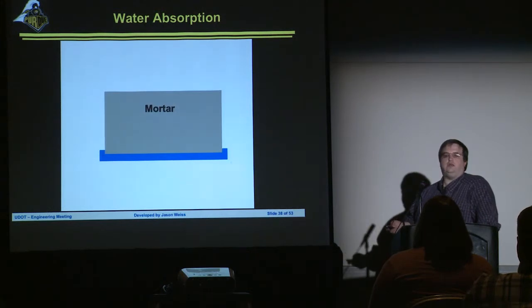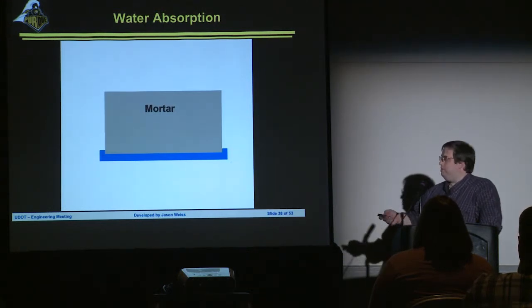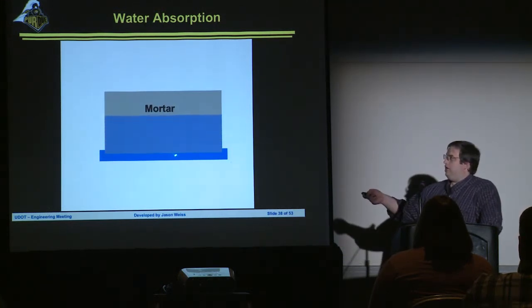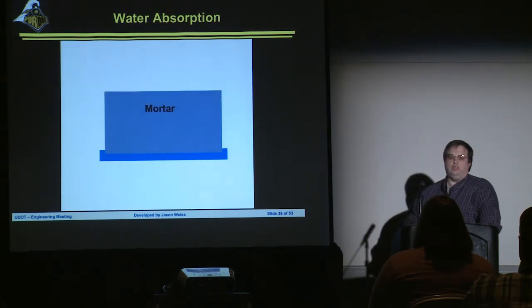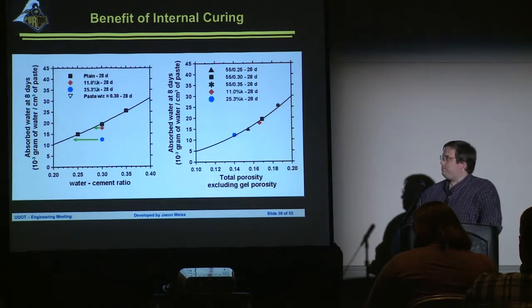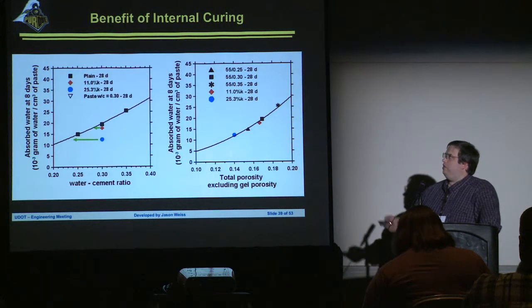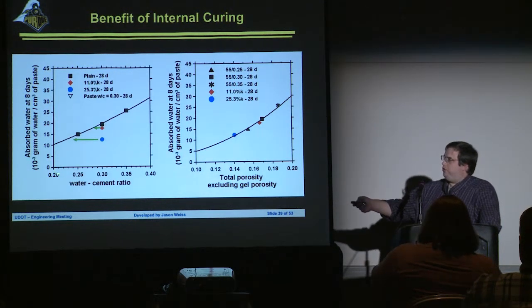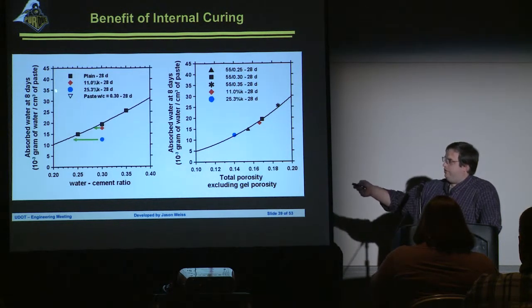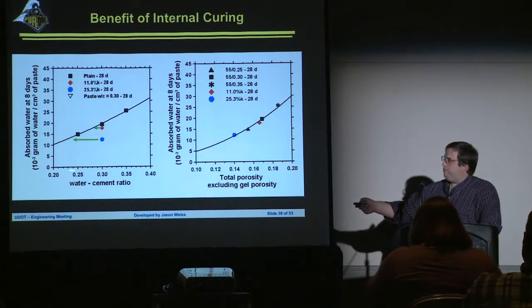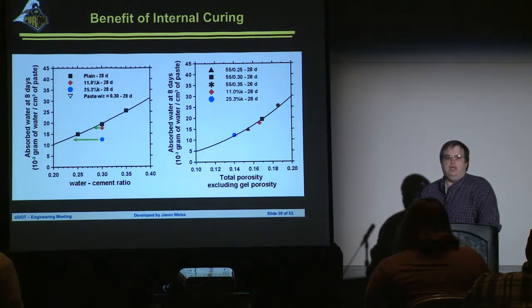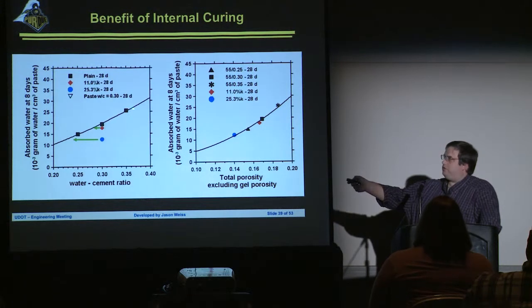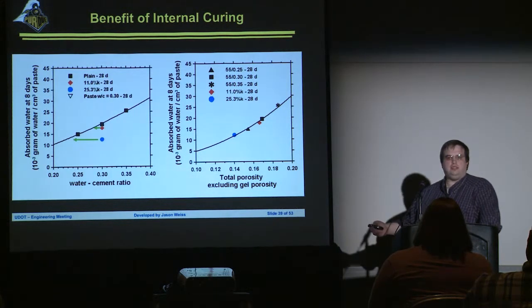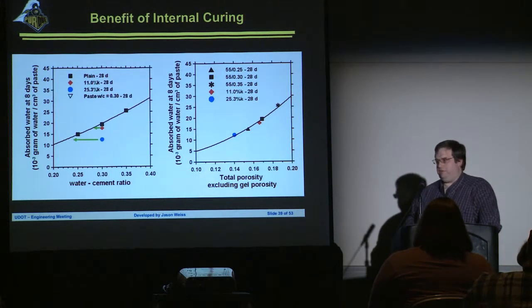Very simple test that can be done to evaluate the performance of concrete. Place a mortar inside of a fluid and measure how fast that fluid gets sucked up into the system. We can do that and we can come up with a plot where we can show either the absorbed water of the system, or we can show the rate of absorption versus the water to cement ratio. Not surprising, higher water to cement ratios have more porosity in the system, they suck up more water. Doesn't shock anybody in this room, I'm sure.